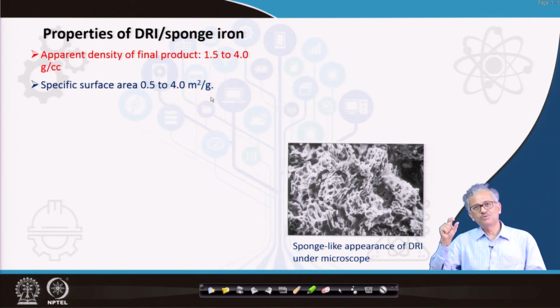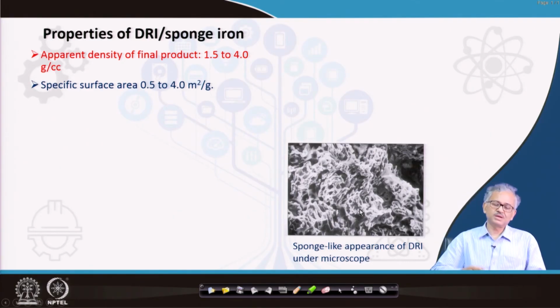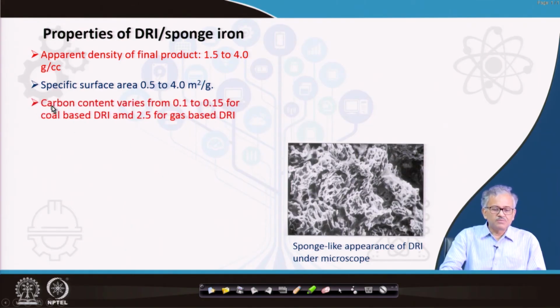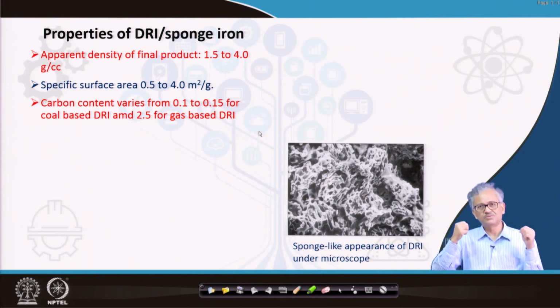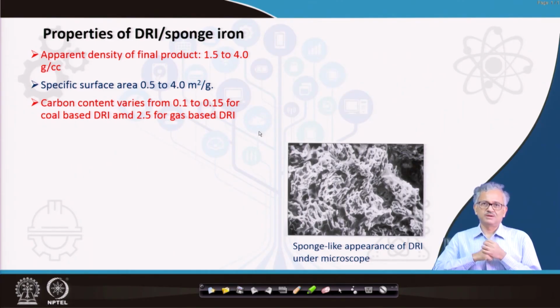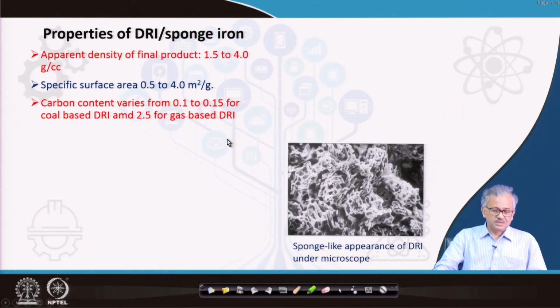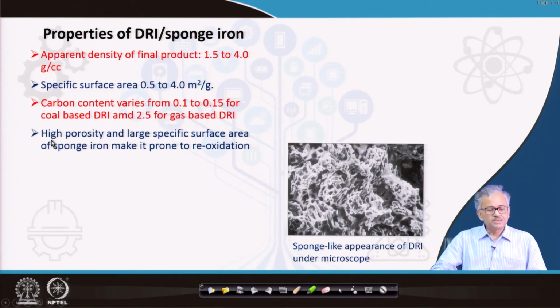And this is the sponge iron. As I said, this is the sponge-like appearance of the DRI under the microscope. If you take the solid piece in your hand, it will not look like a soft sponge. It is a very hard material. But if you see the microstructure, you can see a lot of pores. These are the pores you can find. So it appears like a sponge. That's why it is called sponge iron. Carbon content varies from 0.1 to 0.15 for coal-based DRI and 2.5 for gas-based DRI, as I said. This is 2.5, very high, because you can control it. Nowadays, even higher carbon in the DRI can be imparted in the advanced gas-based DR processes.